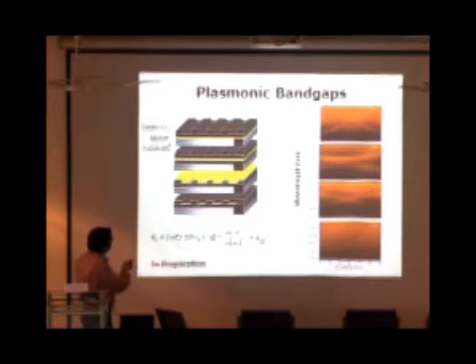But if you have a symmetric structure, where we put a dielectric underneath, a metal on top, and then another dielectric on top and pattern from the top, this is a symmetric structure where the plasmon resonance at the top and bottom interface are identical. So the plasmons excited at the top essentially couple to the plasmons at the bottom interface and then radiate out. So you have very fast lifetimes expected in this case, in which your line width is expected to be very broad.